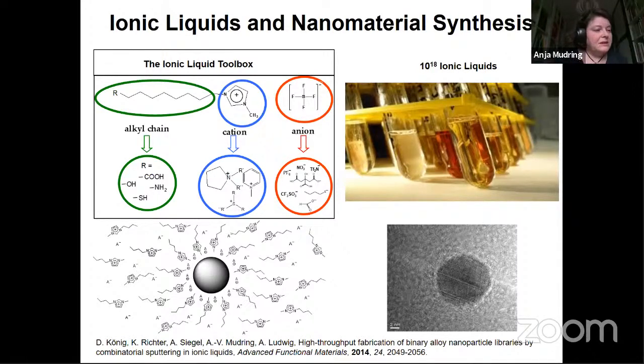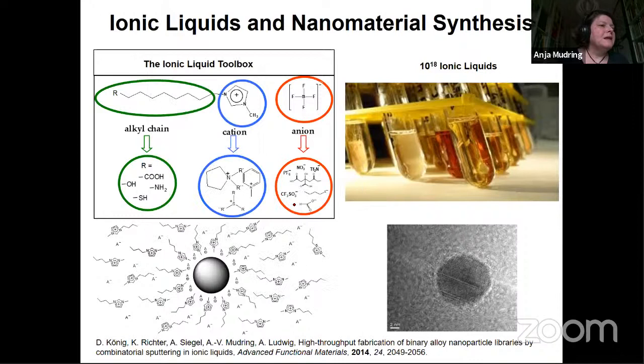So we believe that ionic liquids can stabilize nanoparticles, both electrostatically, but also, when you think of the big cations and anions, sterically. So they attach to the surface and they immediately shield the particles. And on the right lower bottom, you see an ionic liquid and a golden nanoparticle in that ionic liquid.